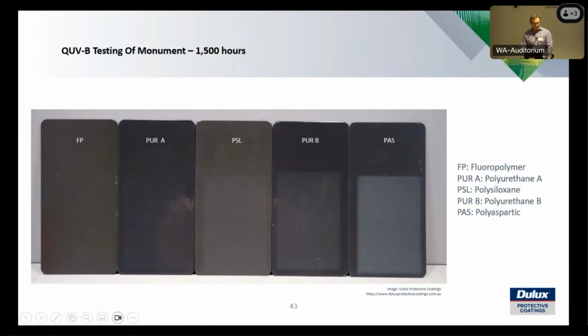The monument, massive change with the polyaspartic and the fluoropolymer still looking good. And look, there can be some colour variation from coating system to coating system too. So those changes with the fluoropolymer and the polyurethane there, they could have been both those were starting points for that particular colour as well. You cannot match exactly sometimes from coating technology to exactly the same. Normally you'd reference as a commercial match.